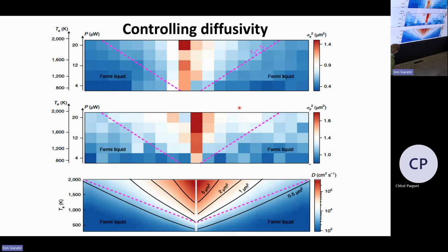So we also did theory on this. This is where Alessandro Principi modeled the whole system, and he can calculate the amount of broadening in this hydrodynamic regime, both in the Fermi liquid and Dirac fluid case. And he can get an amount of broadening that is on the order of a few micrometers when you're close enough to the Dirac point, which is very consistent with what we're seeing in our data. Now, what is interesting about the simulations, and we can actually correlate that with our data as well, is that we can get an estimate of the diffusivity. And what he predicts, and what we also see in our data, is